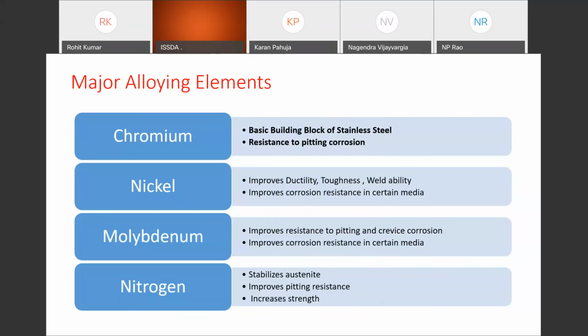Nitrogen: with the advent of new technology in the 90s, argon oxygen decarburization, the ability to put nitrogen into the melt was introduced, which is an austenitic stainless steel stabilizer. In some way, it also improves pitting resistance a little bit, and definitely it increases strength. So nitrogen-bearing stainless steels were also introduced. These are some of the major alloying elements. Apart from that, there are other elements like titanium, niobium, which improve some of the welding properties or malleability properties. But for architecture, building, and construction, we will restrict to the grades and family of grades most widely used in building and construction.